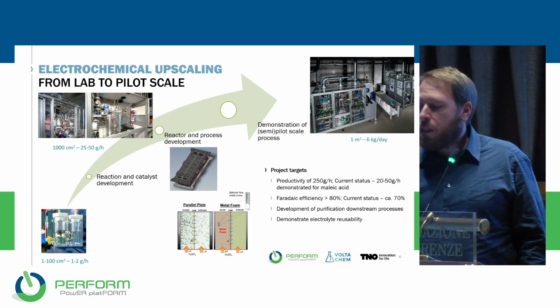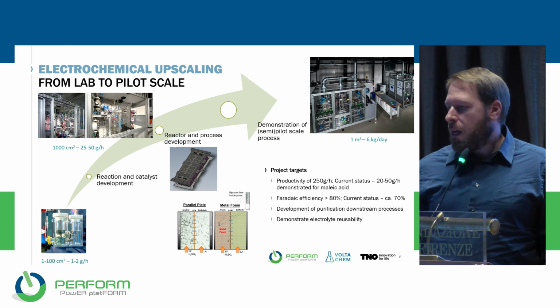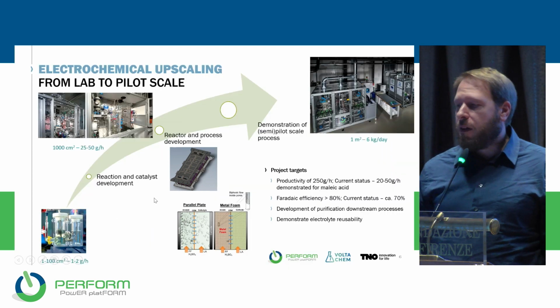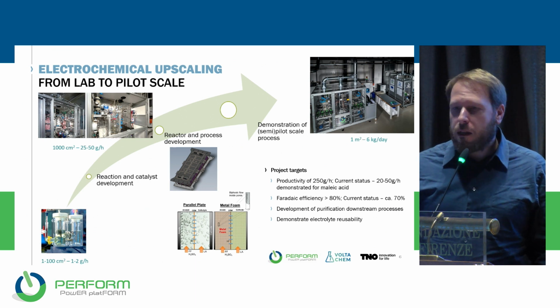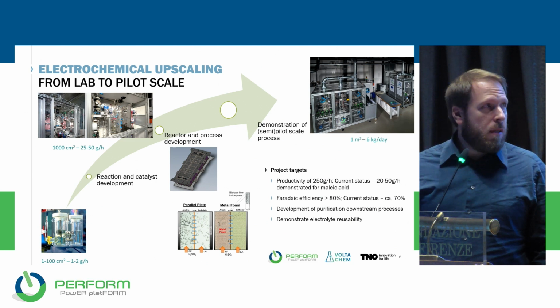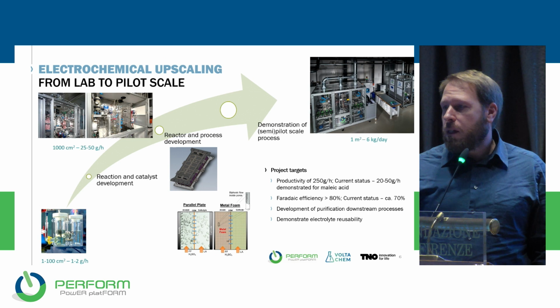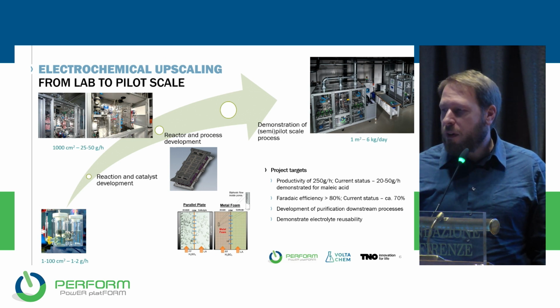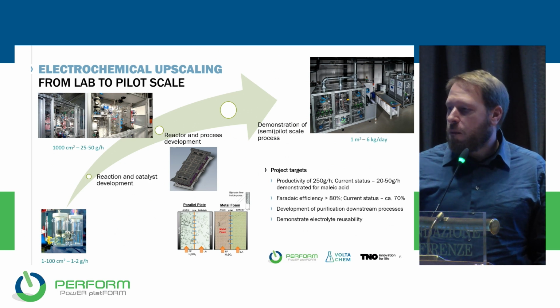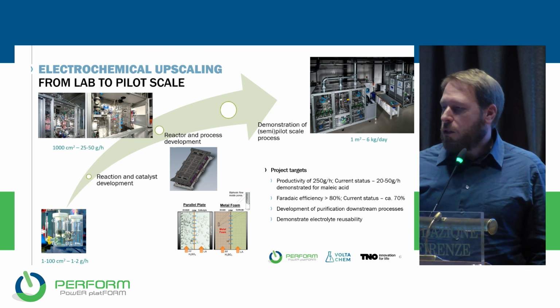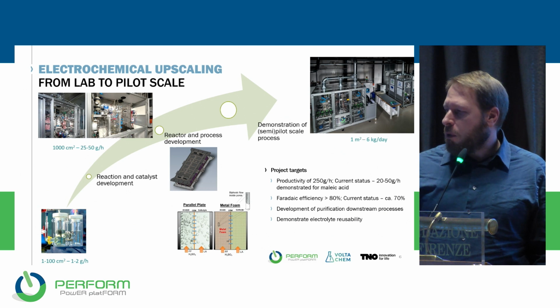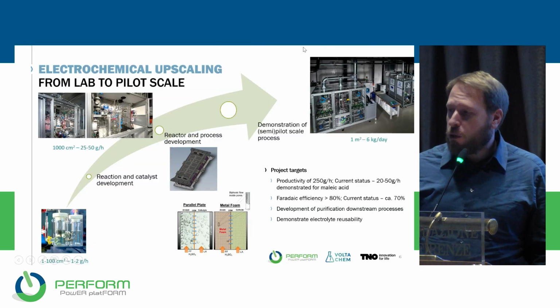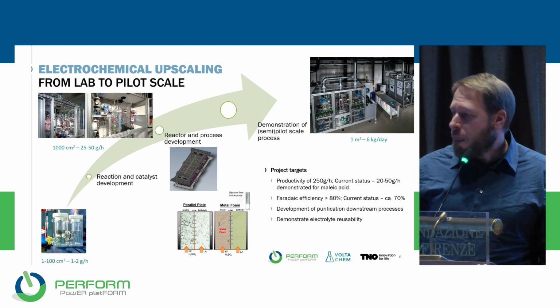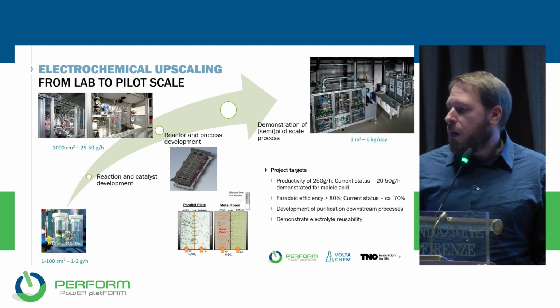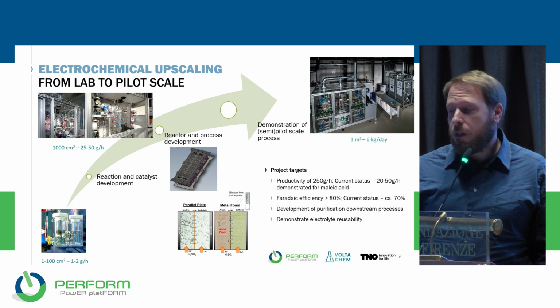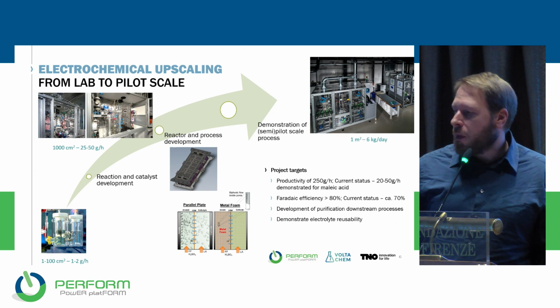So as was already mentioned a few times, in this process we moved from a very low TRL level with very small reactors in the order of a few square centimeters to begin with. Then towards the middle of the project, we reached 1,000 square centimeter electrode surface area with a very small balance of plant around, and from here we did more reactor and process development, in collaboration with the partners, to build the actual power platform that is standing right now in our labs. Targets of the project for this pilot were 250 grams per hour productivity, about 6 kilograms per day, with a very high Faraday efficiency.